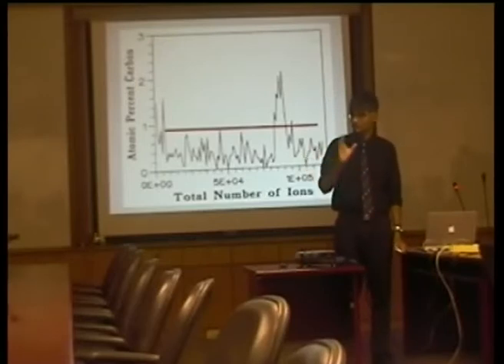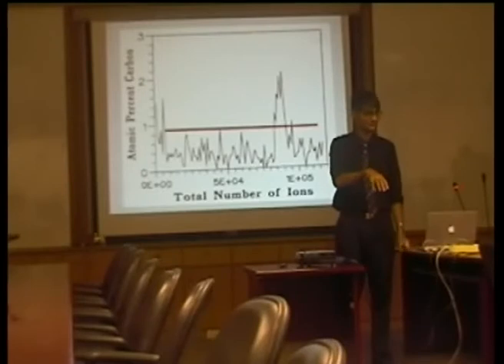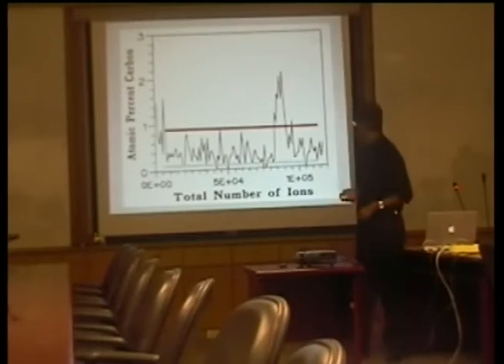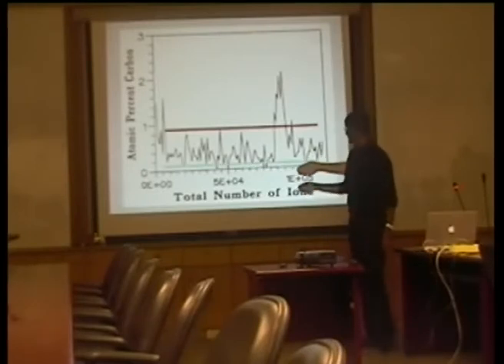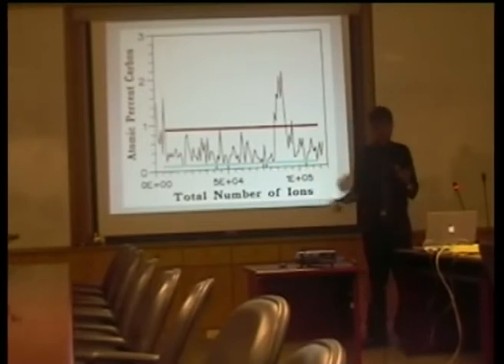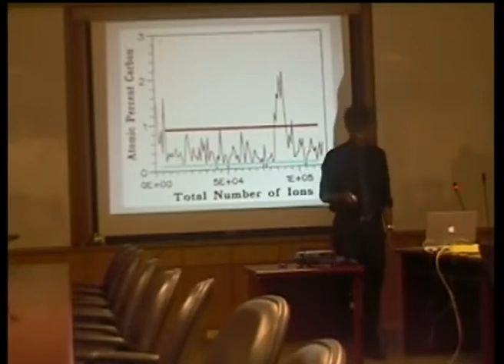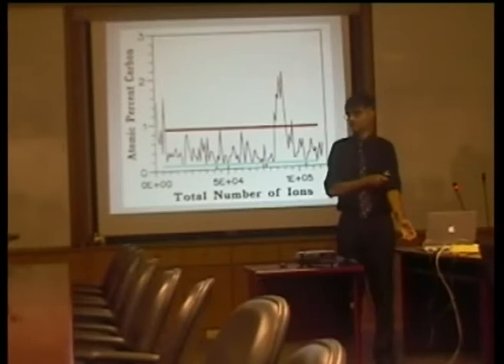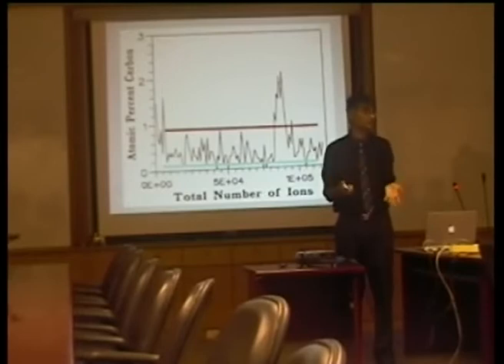We started off with almost zero carbon ferrite, and we've introduced carbon by breaking up the martensite and mixing it with the ferrite. This is how much carbon the ferrite should really contain under equilibrium conditions. So we are far in excess of the equilibrium concentration of carbon. So this is like the process of mechanical alloying, where you start off with elements, you deform them severely, and therefore they form a solid solution.